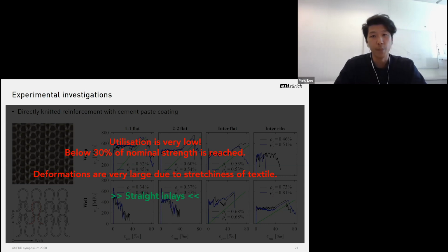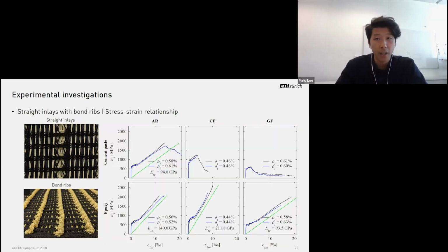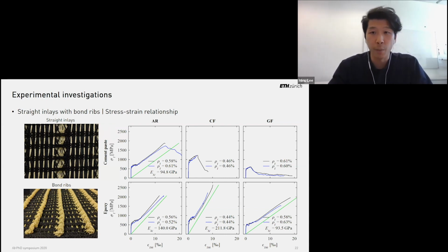And therefore, the reinforcement with straight inlays was hoped to perform better since the rovings are aligned to the direction of loading. So here, looking at the stress-strain relationship for the knitting patterns with straight inlays, 3 different materials, aramid, carbon fiber, and glass fiber, and 2 different coatings, cement paste and epoxy. And we can see that the textile stresses reach much higher values of utilization of around 60 to 70%. But the rovings still do not reach the full filament strength.